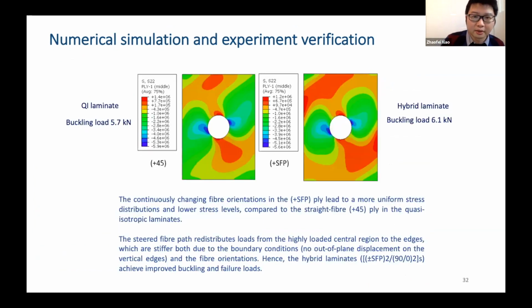And the reason for achieving the better buckling performance is that the continuously changing fiber orientation in the steered fiber ply leads to a more uniform stress distribution and a lower stress level compared to the straight fiber ply in the quasi-isotropic laminates. And the steered fiber path can redistribute the load from the highly loaded central region towards the edges, which are stiffer, but due to the boundary condition, because out-of-plane displacements are fixed, and the fiber orientation, the hybrid laminates can achieve the improved buckling and failure load.